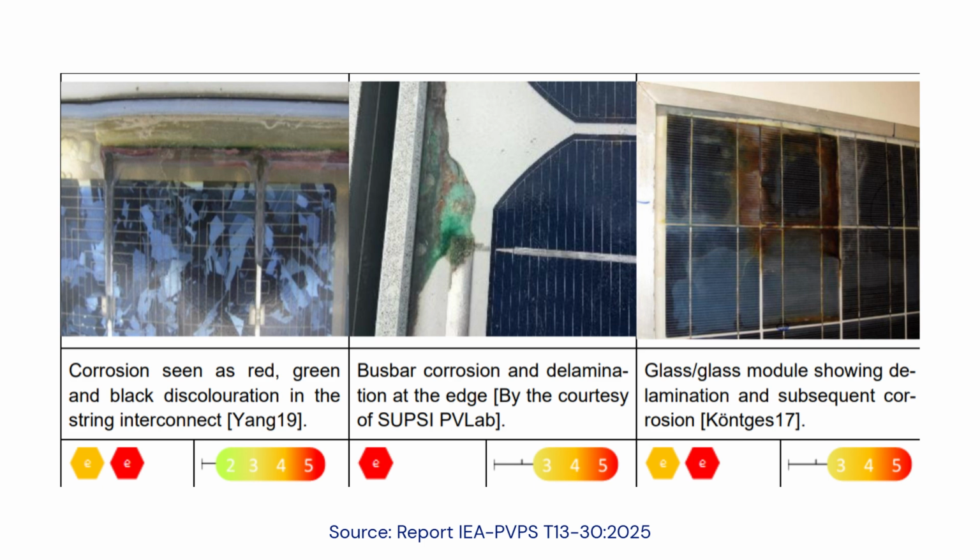The ingress of moisture caused by an ongoing delamination process leads together with the oxygen to a further acceleration of the corrosion. Corrosion can be caused by a poor manufacturing process, like residual crosslinker due to a too short lamination process, imperfections in cell soldering, or the choice of poor materials: low corrosion resistance of tin-based coating of copper ribbons, high water permeability of backsheet and encapsulant materials.